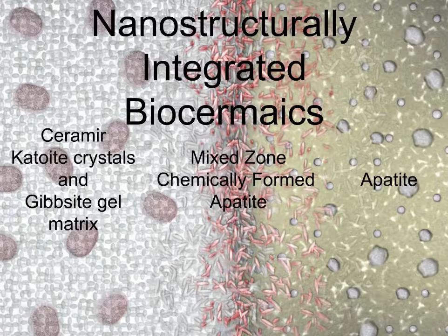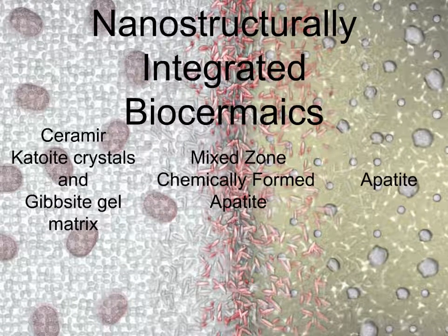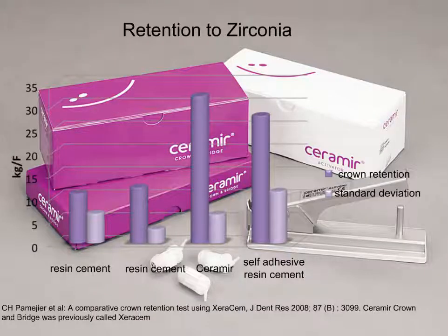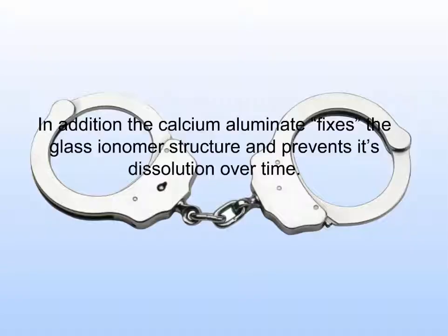When Ceramir comes into contact with apatite, a mixed zone of chemically formed apatite is established. Katoite and gibbsite allow attachment to the tooth structure by nanostructural integration, thus the category of nanostructurally integrated bioceramics. In this study, published in the Journal of Dental Research, the retention of Ceramir to zirconia is higher than that of self-adhesive resin cement. The calcium aluminate fixes the glass ionomer structure and will prevent its dissolution over time.